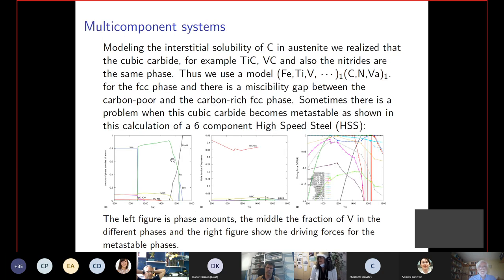And then you can go on to higher order systems. This is a high speed steel with some 5 or 6 elements. And here now phase diagrams are becoming a bit complicated. So I will come back to describe how we describe isopleth phase diagrams. This is called a property diagram. So you just change one variable here, you change the temperature, and you can see which phases are stable at the different temperatures. And you have a liquid at high temperature, you have a small region with the BCC phase stable, and then comes the FCC phase, and then BCC comes back at low temperature, and you have various carbides forming. And when you do a calculation like this, you can look at various properties.